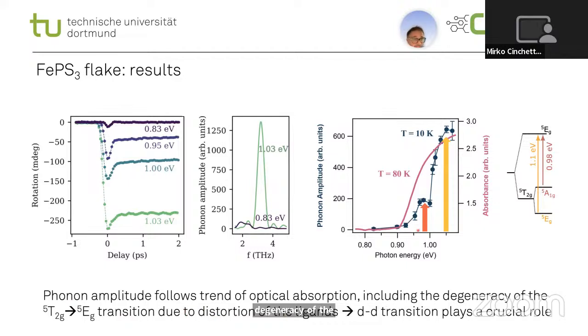So basically what we observe is that when we are in resonance with the d-d transition, we have a strong enhancement of the amplitude of this phonon mode. As I was assuming before, we have a first demonstration that we can use the d-d transition to generate lattice dynamics.